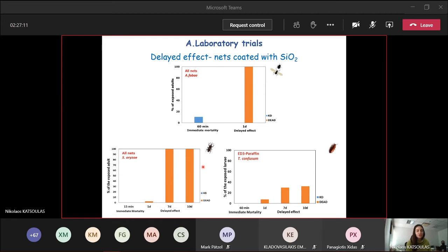As you can see here, concerning the Sitophilus oryzae insects, all nets again proved to be working well. However, we saw an effect 7 days after the exposure of the insects for 15 minutes to all nets. However, in the case of Tribolium confusum larvae, it is obvious that none of the tested nets proved to be efficient. The only result that we can present here is from the ED3 net coated with paraffin, in which the mortality rate did not exceed 30% even 10 days after the exposure.